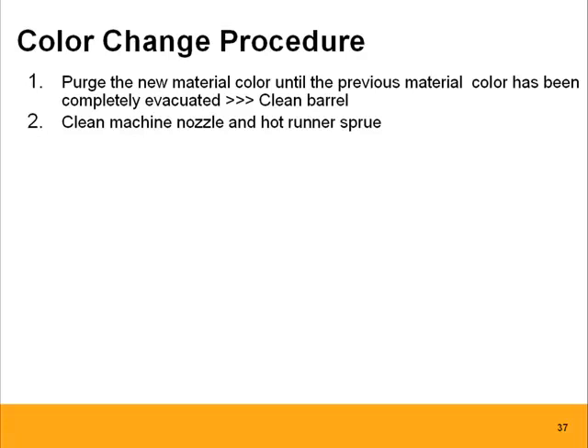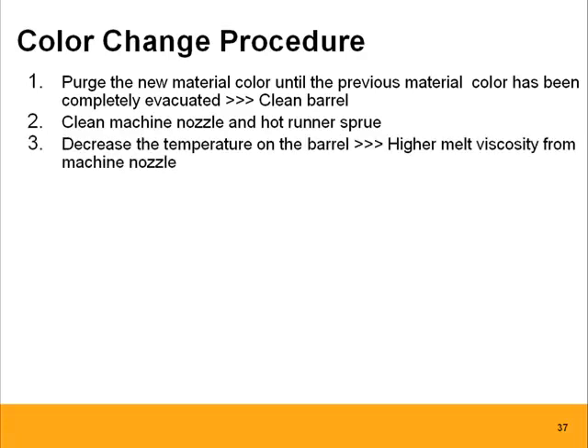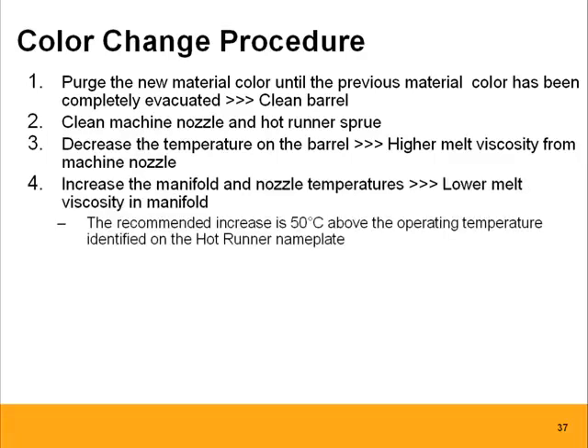Then decrease the temperature on the barrel, because what we want to create is higher melt viscosity from the machine nozzle. We want that tougher material pushing out that lower viscosity material. And how do we achieve this? If we do it with the same resin, we increase the manifold and nozzle temperature. That will lower the melt viscosity in the manifold, in the melt channels, and the nozzles. The recommended increase is around 50 degrees Celsius above the operating temperature that's given by the hot runner supplier. And in the case of Husky, it's written on the side of the hot runner.